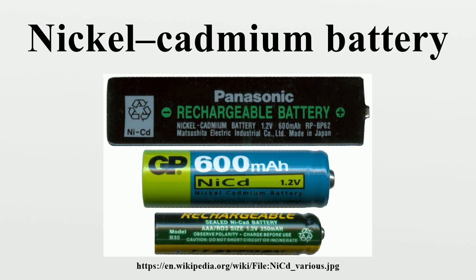Some specialized batteries can be charged in as little as 10 to 15 minutes at a 4C or 6C charge rate, but this is very uncommon. It also exponentially increases the risk of the cells overheating and venting due to an internal overpressure condition. The cell's rate of temperature rise is governed by its internal resistance and the square of the charging rate. At a 4C rate, the amount of heat generated in the cell is 16 times higher than the heat at the 1C rate. The downside to faster charging is the higher risk of overcharging, which can damage the battery, and the increased temperatures the cell has to endure.